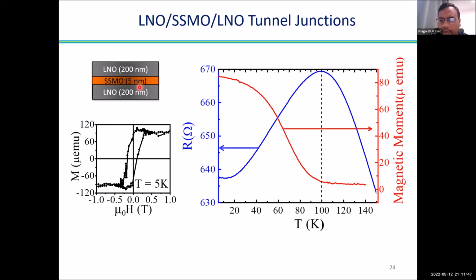It's always a little bit here and there. In fact, within the film itself, if you make a small film, like a small part of that, the TC will be a little bit here and there. So TC is not always the same, especially when you make devices. And so that is one reason. The other is that this is more of a phase separated system. So though the TC of the bulk system that we see is around 100 Kelvin, it started showing behavior of some metal to insulator transition or percolation at an even slightly higher temperature. So that is somewhere around here. And the interface also plays a role. What is happening at the interface, these tiny details, is difficult to know.